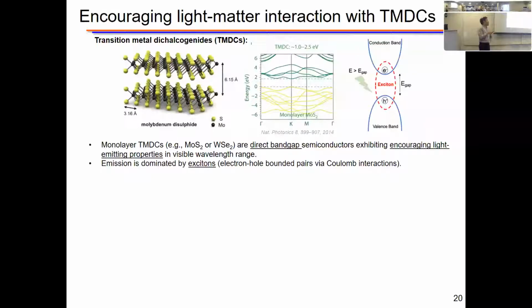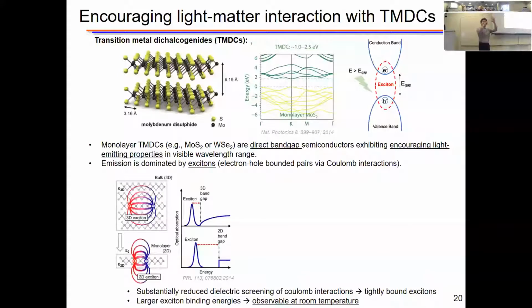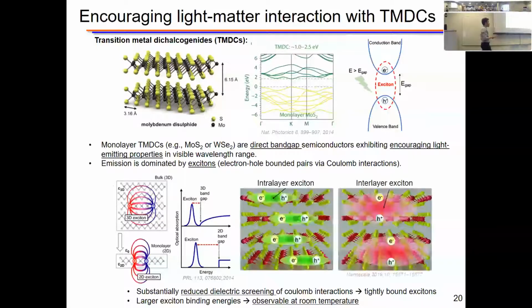And that creates this electron-hole quasi-particle, bound by Coulomb interaction, which is called an exciton, arising from the low dimensionality. What I mean by that is, when we go down from bulk to two-dimensional, we can substantially reduce the dielectric screening, which gives us this large excitonic binding energy. This actually enables us to realize excitonic devices operable at room temperature.